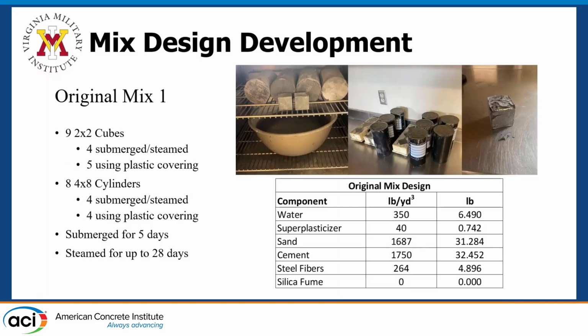So here's our original mix 1. We did 9 2x2 cubes, 4 submerged, 5 using plastic covering, 8 4x8 cylinders. We submerged each one for 5 days completely, and then we steamed for up to 28 days after that. So here's our mix design for that. We'll go into the 28-day break strength afterwards.